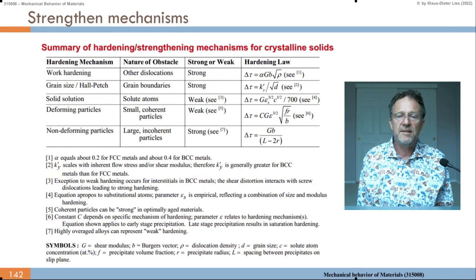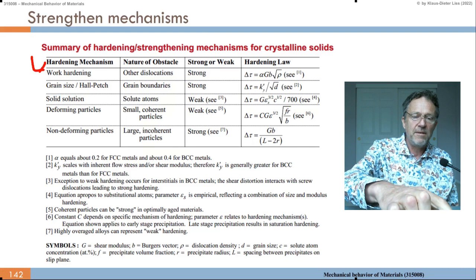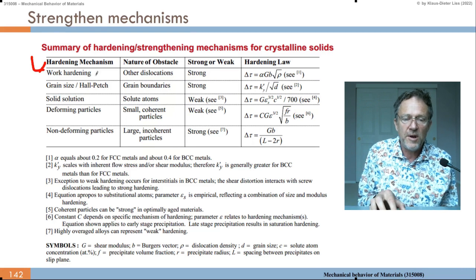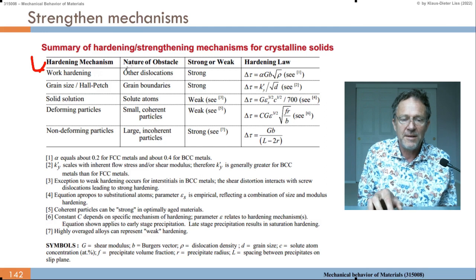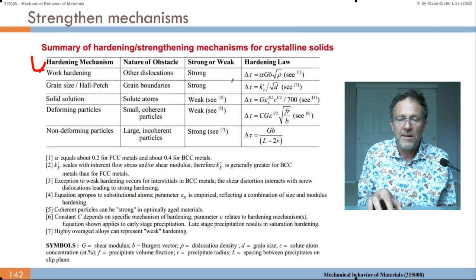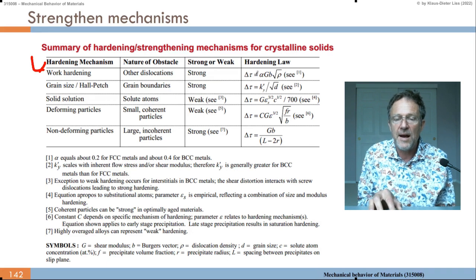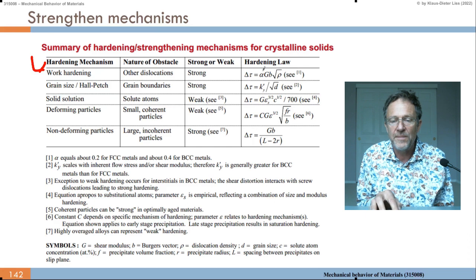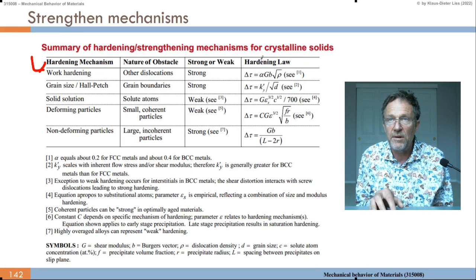Here's a summary of the hardening and strengthening mechanisms for crystalline solids. Again, we have the typical aspects here: the work hardening, the nature of the obstacle, there are other dislocations. So dislocations and other dislocations, they repulse each other, they entangle each other, they may interact with each other, attract each other, and it's relatively strong. And the hardening law is delta tau, the increase in the shear stress from the undistorted material to the hardened material, equals alpha, some constant alpha. Here alpha equals about 0.2 for FCC metals and about 0.4 for BCC metals. So this is some constant we can calculate or estimate or get empirically.